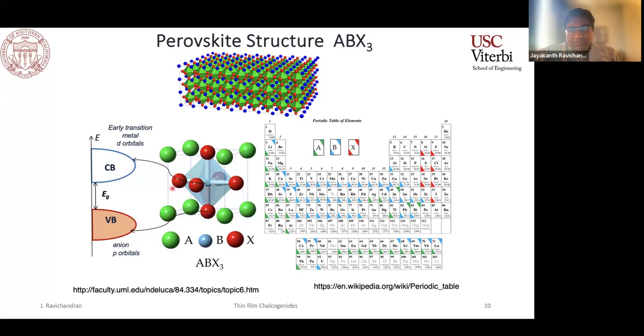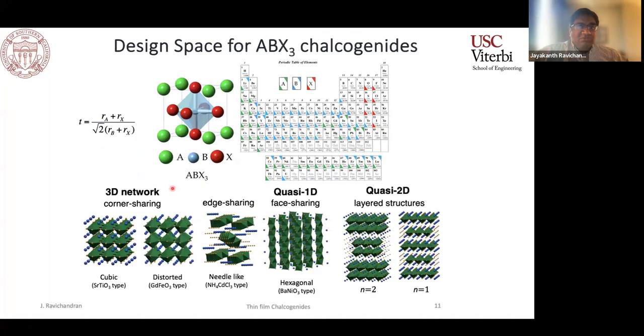And of course, this perovskite structure comes from calcium titanate, which is the prototypical material based on which the perovskite structure was discovered. And if you take this framework and you start thinking about changing your A, B, and X elements, the nature of how you connect all these octahedra together changes dramatically. For example, if your ABX3 closely follows the Goldschmidt tolerance factor, then you can have this corner shared perovskite-like structure, either cubic or distorted perovskites, or you can force the system to have edge sharing, where instead of the corners, you're now connected through the edges, and that leads to lower dimensional systems. And you also have this quasi 1D face-shared system where you can have highly anisotropic 1D chains running along the C-axis, and there is a hexagonal tiling on the AB plane.